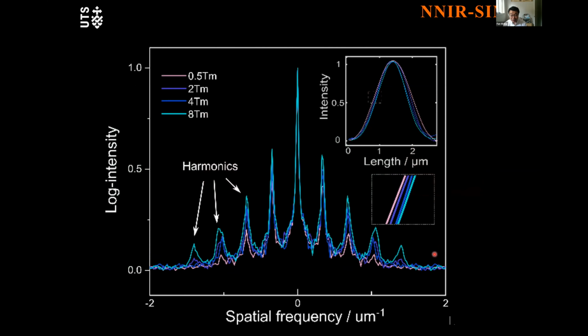And if you look at the frequency domain, if you're shining some pattern onto your material and you have this response, in the spatial frequency domain you will see that if we increase the doping concentration, you pretty much increase your nonlinearity. Therefore your high harmonic peaks over here, first, second, third, fourth order, come to be really, really high. Which means that in this material, it's really easy to achieve high harmonic emission.